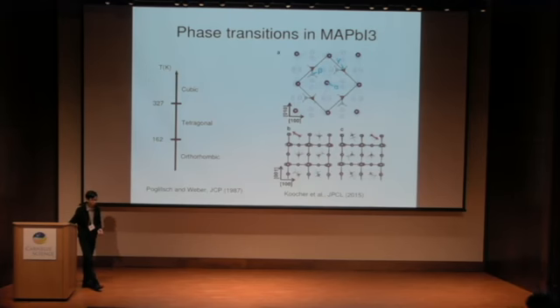So if I understand correctly, you're asking if the bonding in the tetragonal phase is different than in the cubic phase. No, I have not looked very carefully at the bonding in the cubic phase, because for my energy structure database, I was actually using lattice constants more comparable to the tetragonal phase. So I don't really know what the bonding is like in the cubic.